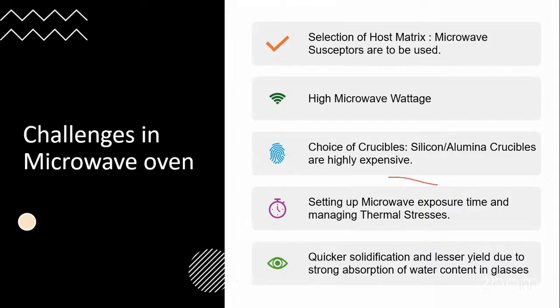with respect to melt quench technique, I had a lot of window open to synthesize glasses. But with microwave, I have to be very cautious. I have to choose a proper host matrix which is susceptible to microwave. Second, the microwave wattage has to be nearly greater than 800 watts. Lesser than that, the window of obtaining the glass is very small, and the probability of formation of glasses is also very low. And the choice of crucibles that we use for the microwave should also be susceptible.